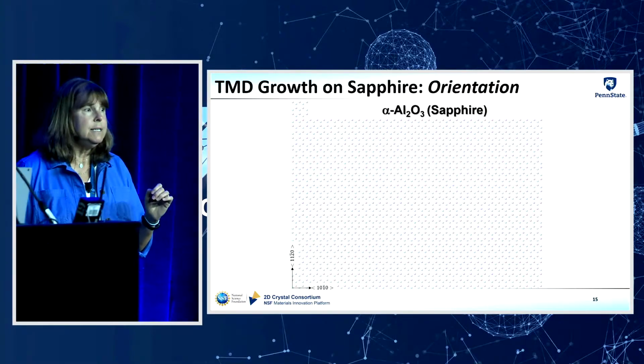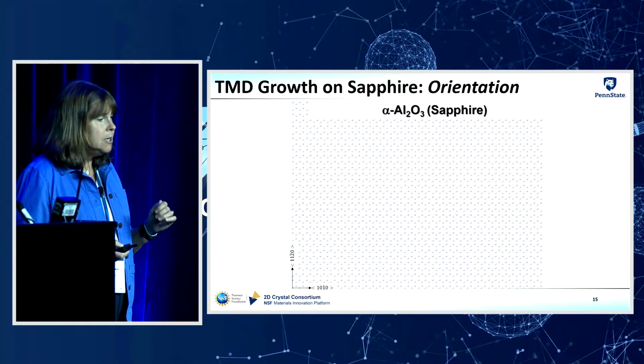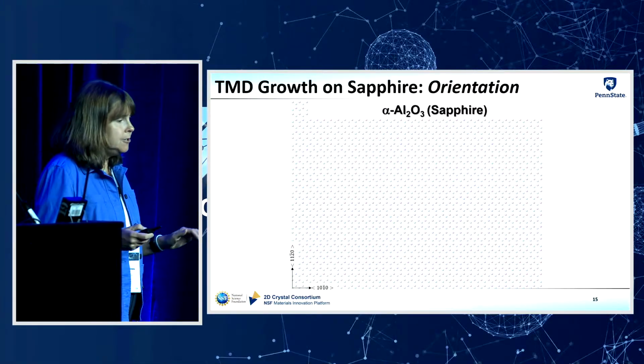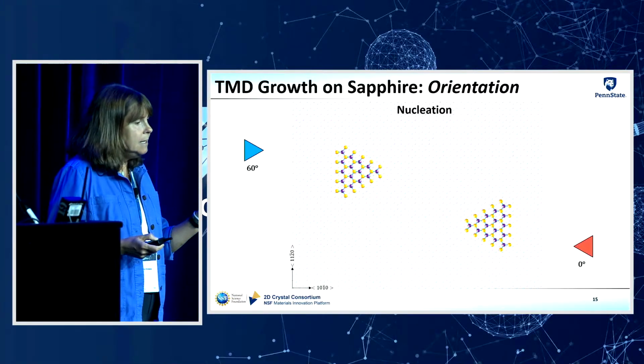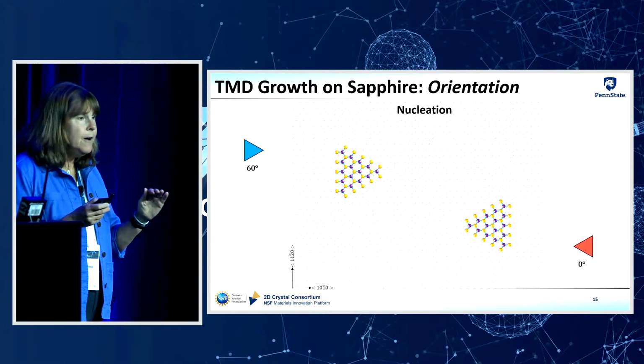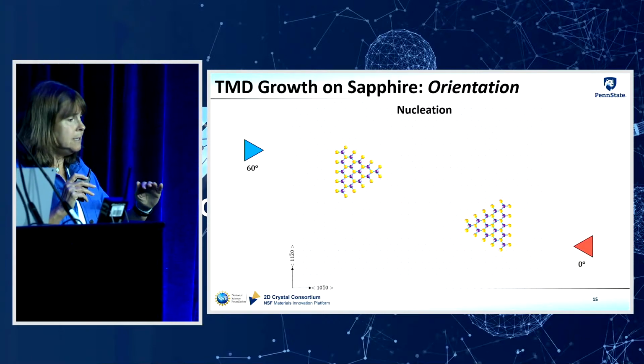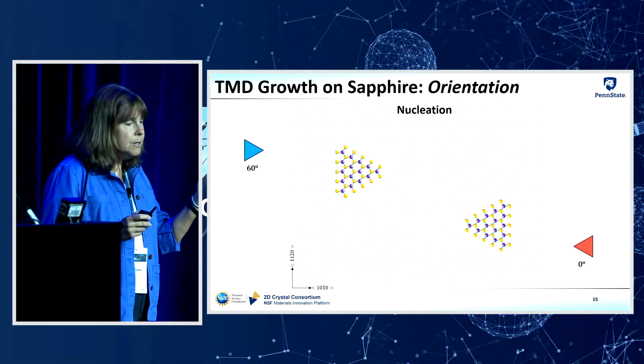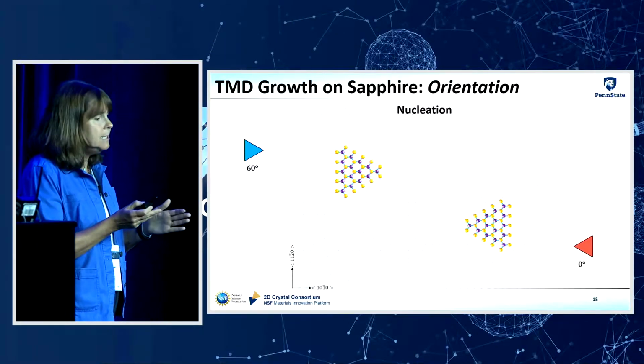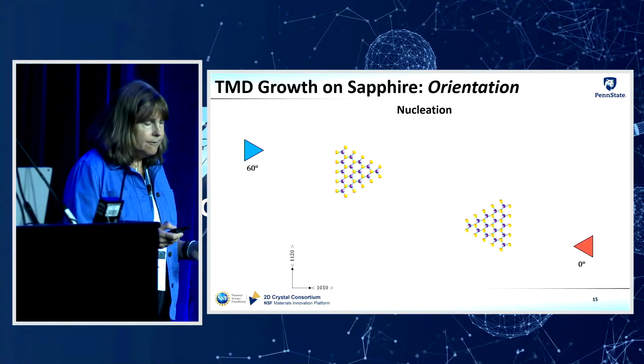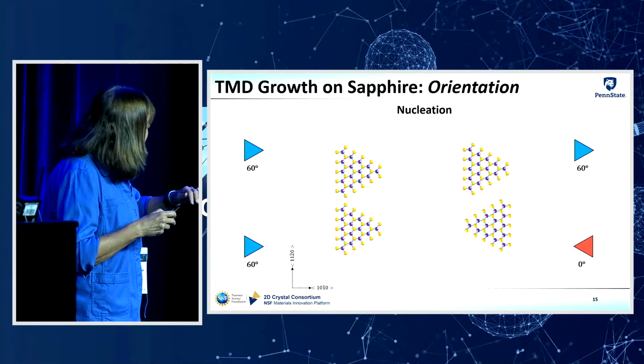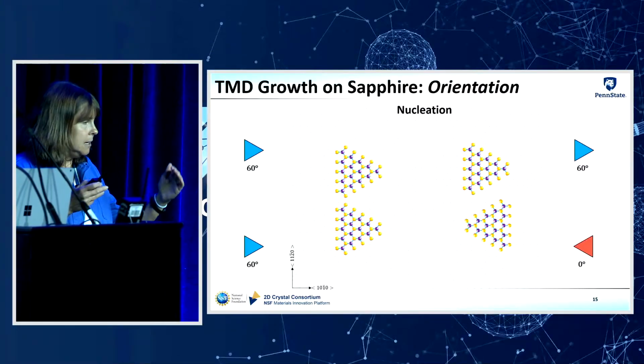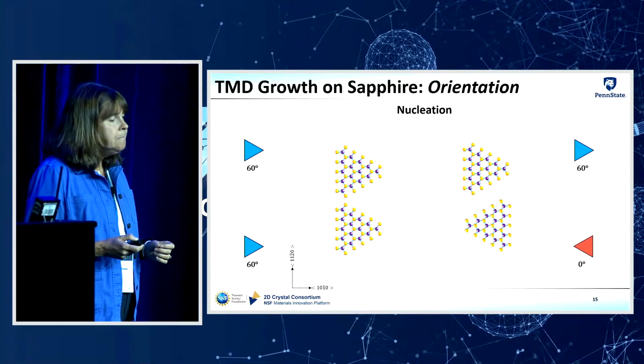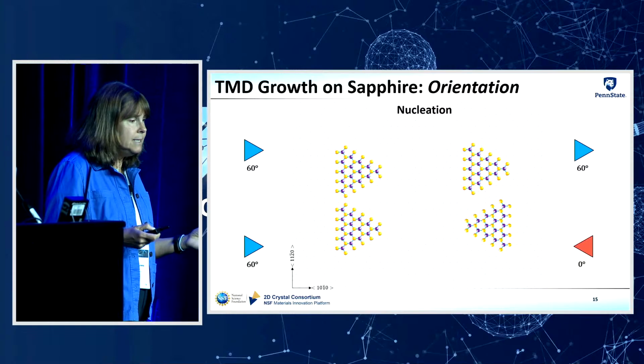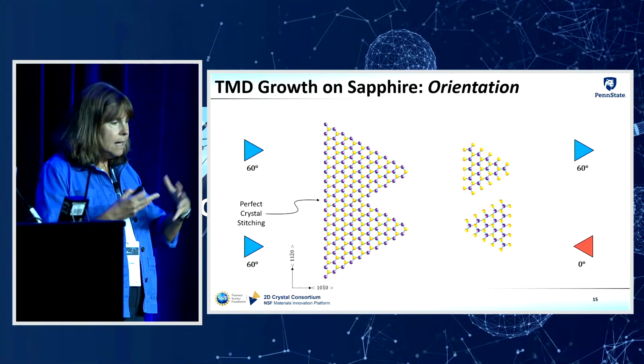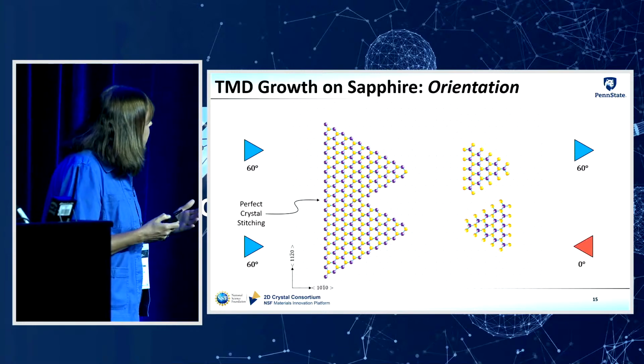Another problem that's encountered is the orientation of the TMD domains. So if we just consider a flat C-plane sapphire surface, if we start nucleating the TMD domains on sapphire, we find that there are two orientations that are energetically similar. These are referred to as the 0-degree orientation and the 60-degree orientation. That's just the orientation of the TMD relative to the underlying sapphire. Now, if we start nucleating nearby domains and we think about how they're going to coalesce and what type of grain boundaries might be formed, what we see is that if we have domains that are oriented in the same direction, when they grow and they come together and they coalesce, they can do so without forming a grain boundary.